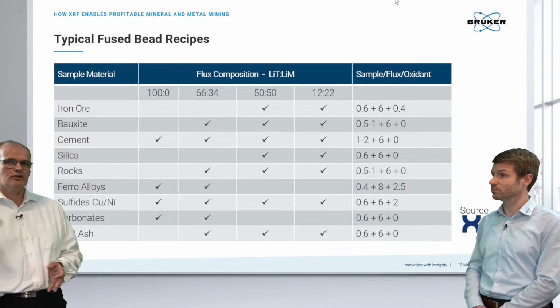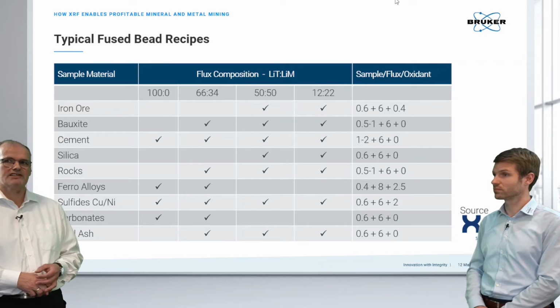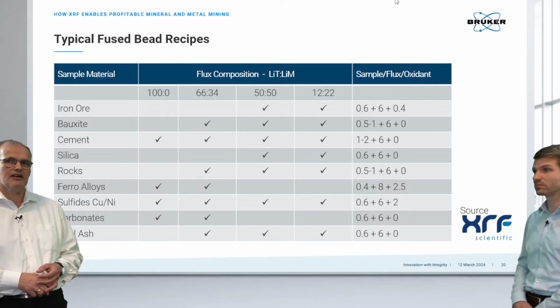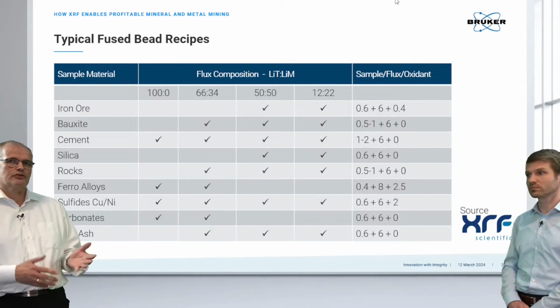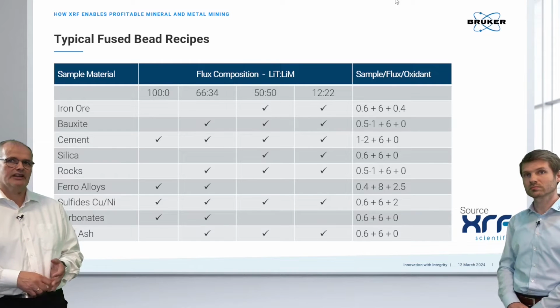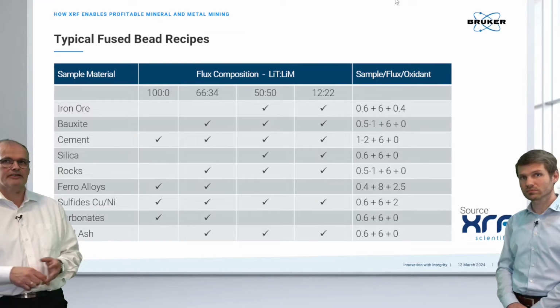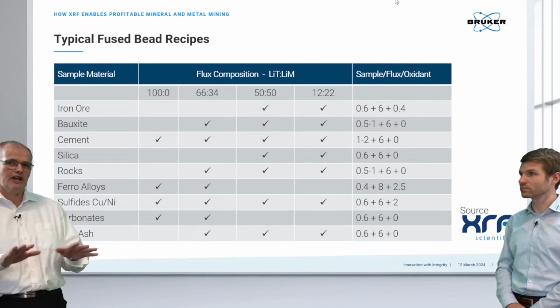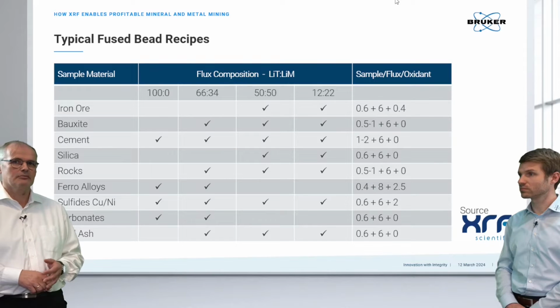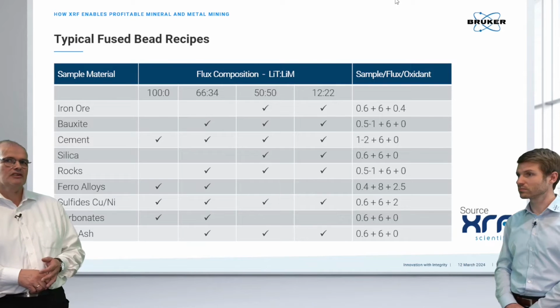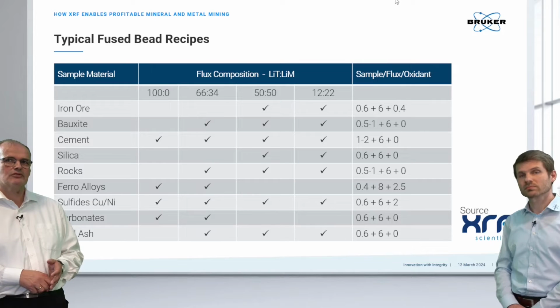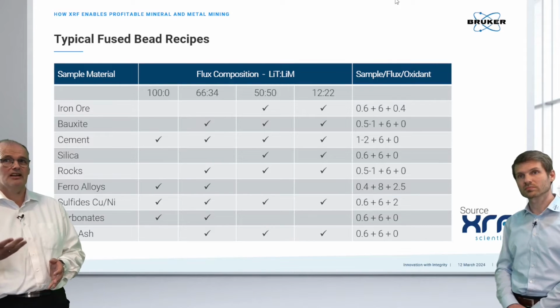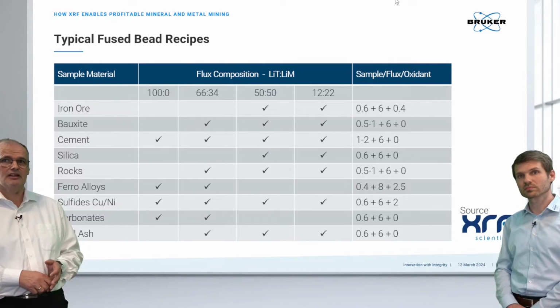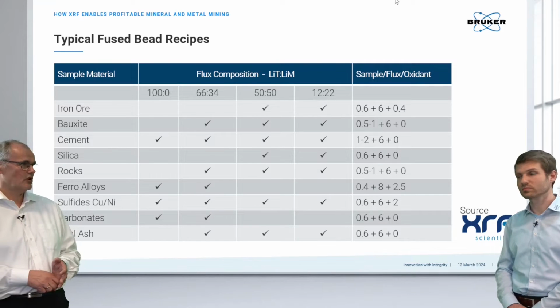Yeah. So here you find a table from our friends XRF Scientific. They have come up with recipes. And what you see is that we can have lithium tetraborate and lithium metaborate in a mixture. So actually we are fine-tuning the melt temperature. And you can see that there are different materials. So like cement is very easy to fuse. So it can be a very high sample amount within a lower amount of flux. And then we don't need an oxidant.